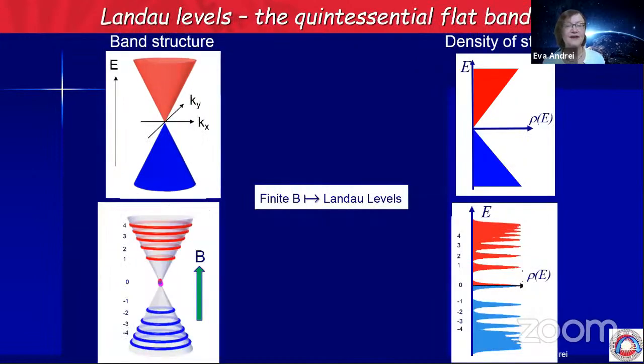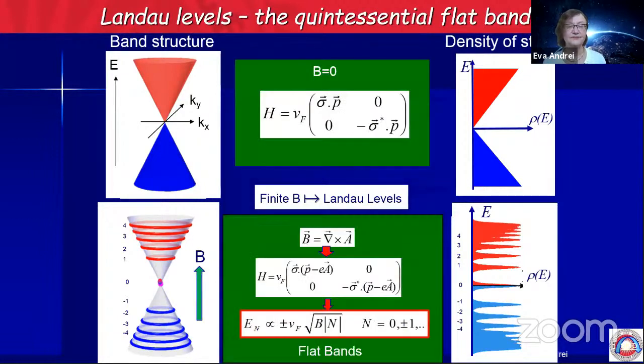Now, if you add an out-of-plane magnetic field, what happens is you break up this band structure into what we call Landau levels, and the density of states now breaks up into these almost flat bands. And you can count them. The one that sits at the Dirac point is n equals 0. If you go into the electron sector, they're positive. If you go into the hole sector, the Landau levels are negative here.